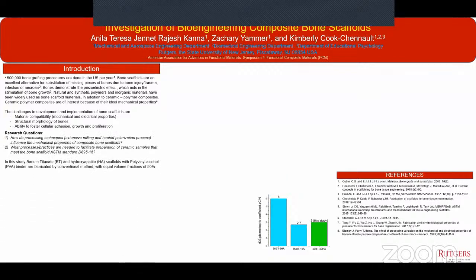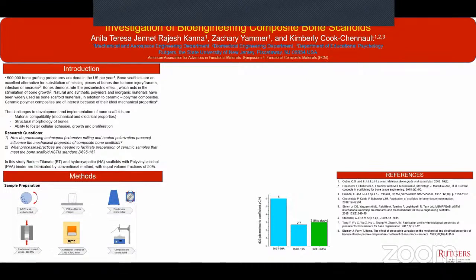So in this work, the research questions are: how do the processing techniques influence the mechanical and electrical properties, as well as what types of processes and practices can be used in order to achieve the ASTM standard that's used for testing bioengineered scaffolds. A conventional sintering mix and mold process was used in order to fabricate these samples, where what should be noted is that a two-step milling process, as well as a parametric study for optimization of the polarization process, was used in order to facilitate the fabrication of scaffolds that mimic